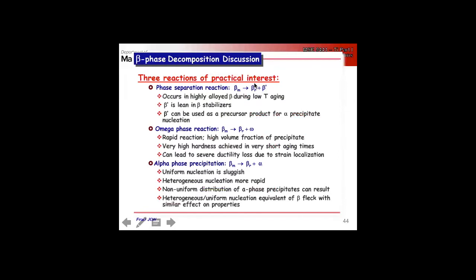And whereas in the alpha plus beta alloys, the beta prime tended to be beta rich in beta stabilizers, in highly alloyed beta alloys, the beta prime is going to be lean in beta stabilizers, right? And the matrix is going to be rich. And just as before, the beta prime regions are going to be precursors for alpha precipitate nucleation, right?